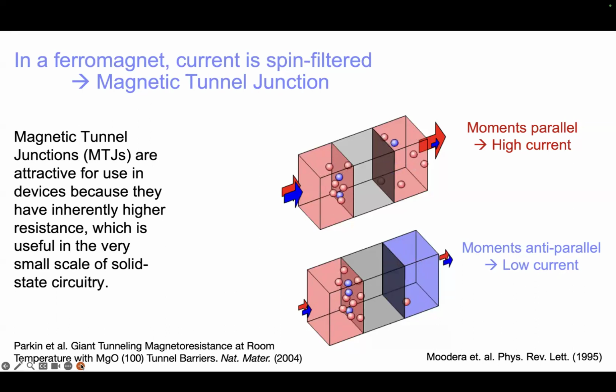This means across that gray insulating region, the S-like wave functions can more rapidly, more easily tunnel than the D-like wave functions. And this automatically leads to a spin filtering effect, meaning that the current in such a device can be up to 96% spin polarized electrons with one spin orientation if the insulating layer is sufficiently thick. And this is something I published in 2004 and is now the basis of sensing devices, spin valve sensing devices using spin-dependent tunneling. And that's been used in magnetic disk drives since 2007.